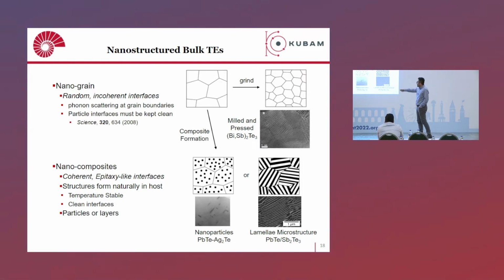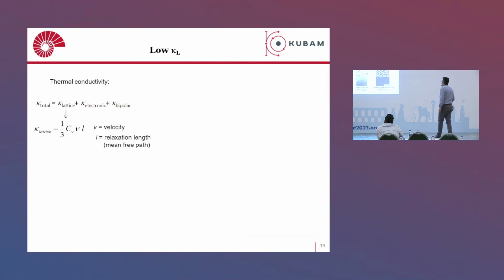So you can also create nanocomposites. Which means you can, for example, introduce intentionally some, let's say, secondary phases either within the grains or at the grain boundaries, and they also act like phonon scattering centers. This is nicely shown, for example, for nanoparticles of lead telluride inside the silver telluride, or by using the phase diagram of these systems, you can create such eutectic structures, and these are lamella structures of lead telluride and antimony telluride. They have also an impact on lowering the thermal conductivity.